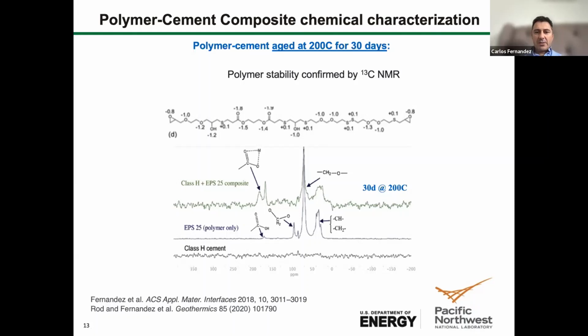And what we see here, for example, for thermoset epoxy, we aged this material at 200 Celsius only for 30 days, which is obviously not the 30 years that is the average lifetime of a wellbore, but it's a way to say, okay, after 30 days, we still see the polymer. We have some changes in the peaks, even after 1 day, but the changes are due to the interactions.